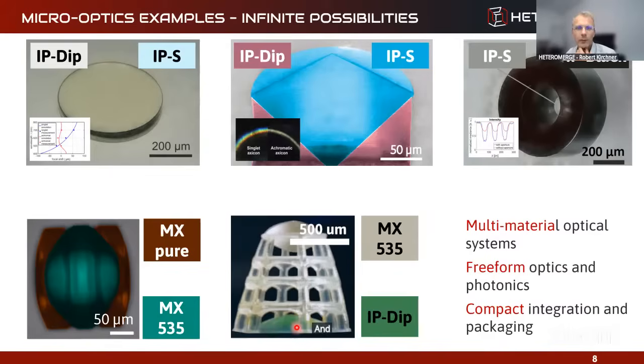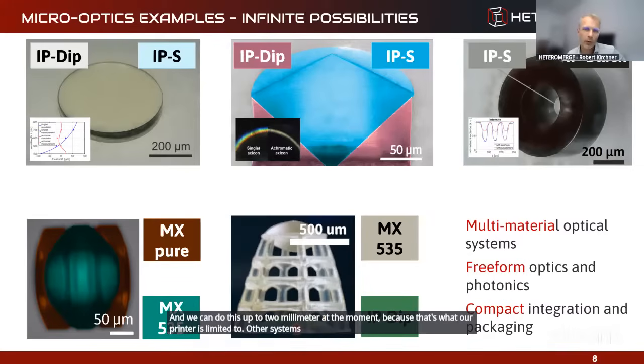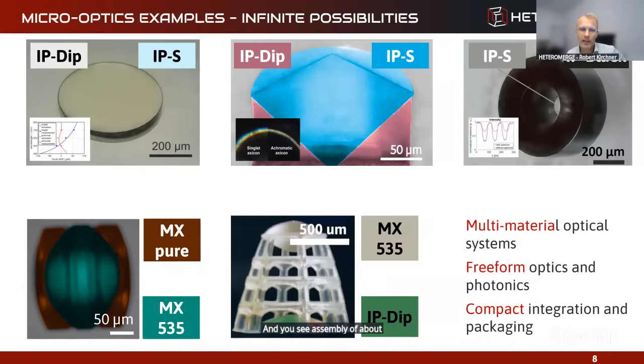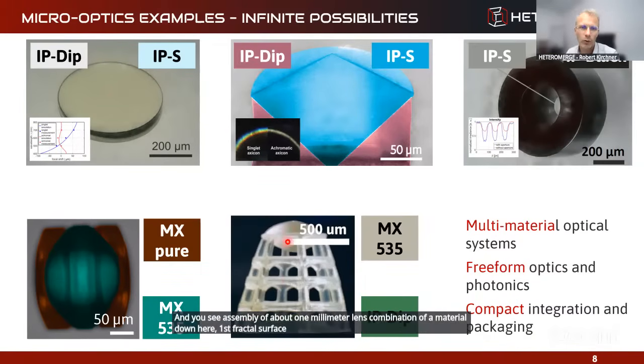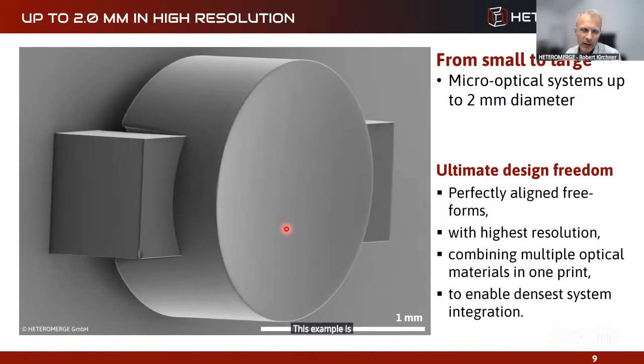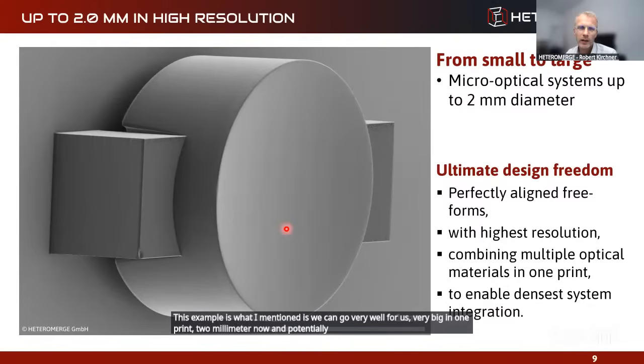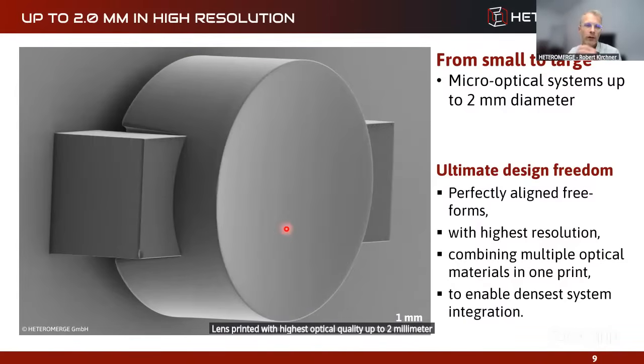There's no limit to the geometry basically you do. And we can do this up to 2 millimeter at the moment because that's what our printer is limited to. Other systems can go up to 3.5 millimeter, close to 4 millimeters. And you see assembly of about 1 millimeter lens combination of a material down here, first spherical surface, and another more complicated surface following on top. This example is what I mentioned: we can go very big in one print, 2 millimeter now, and potentially later soon 3 to 4 millimeter without any stitching. So it's a full lens printed with highest optical quality up to 2 millimeter without any stitching for this material.